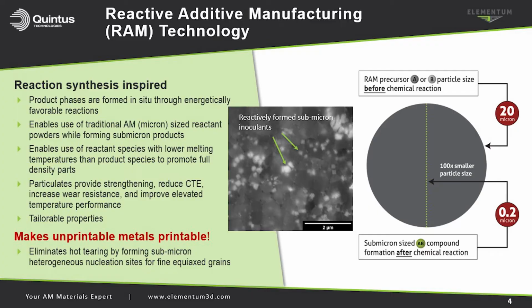Very exciting. Jeremy, can you give us a little bit more detail about your reactive additive manufacturing material system and what that means to AM? Reactive additive manufacturing is reaction synthesis inspired, where we're using precursor phases to form product phases in situ during the AM process. These in situ formed product phases provide a lot of great benefits, including dispersion strengthening to improve the properties of the material, but they can also serve as inoculant sites to heterogeneously nucleate the grain structure of these materials, leading to a more equiaxed, fine-grained microstructure with improved properties, including solving a lot of the printability challenges that the traditional materials might face.